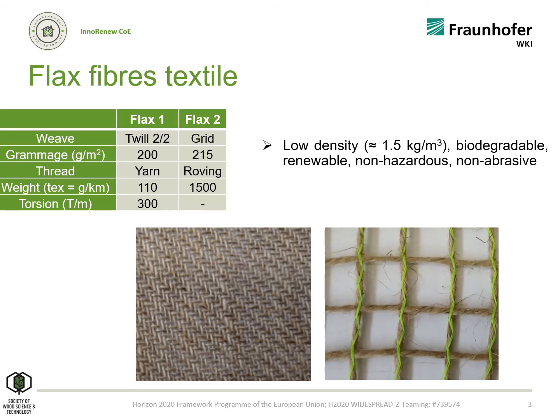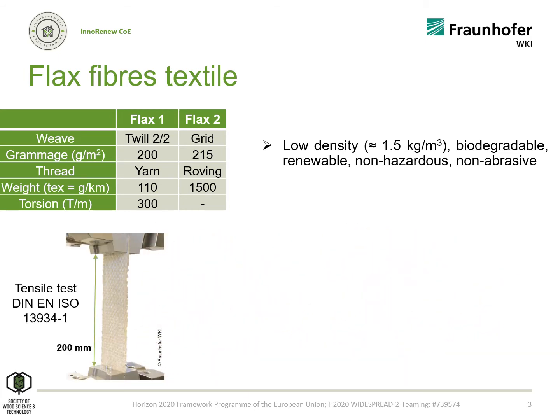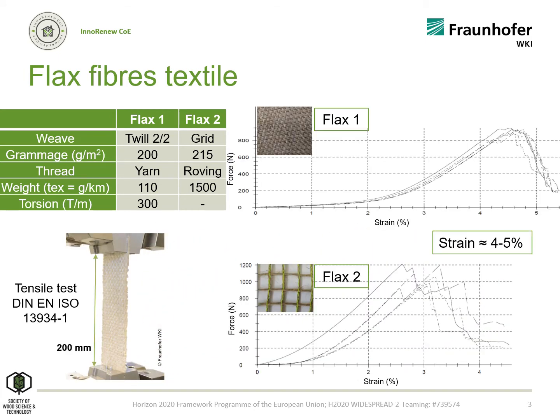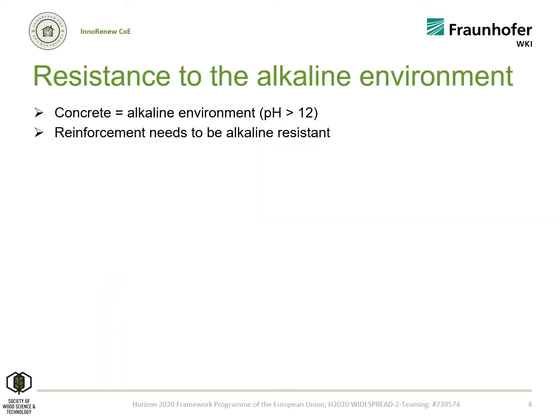We characterize them by a tensile test, and the force strain curves show that there is a first part corresponding to the load of the flax fibers before they are pulled together and really play their reinforcement role. This happens around 2.5% for flax 1 and 1% for flax 2. It actually corresponds to 5 and 2 mm strain respectively.